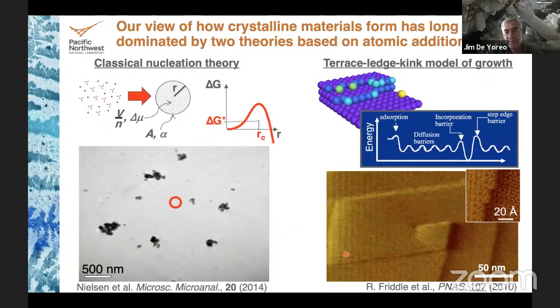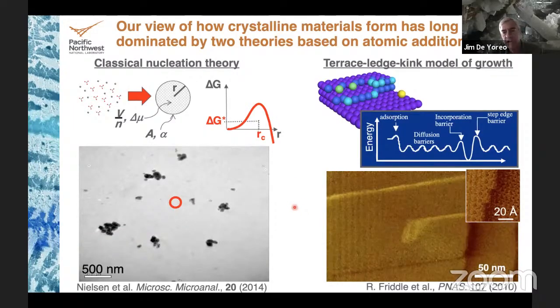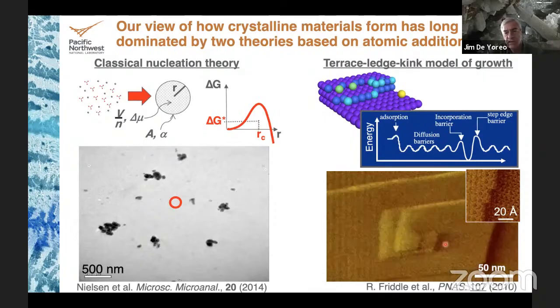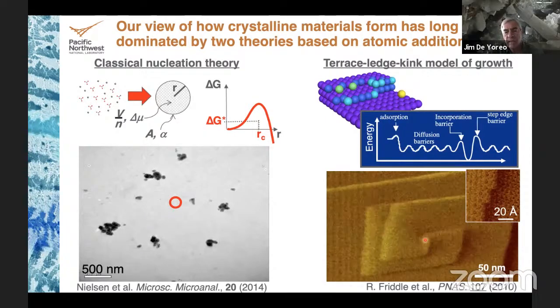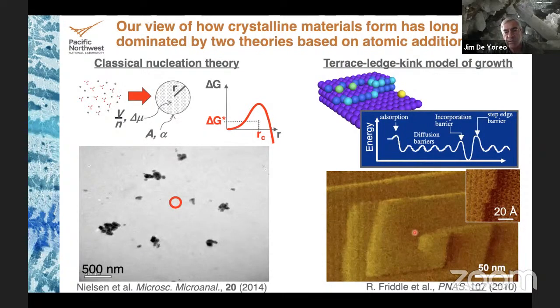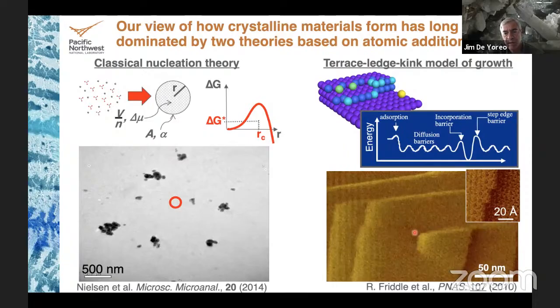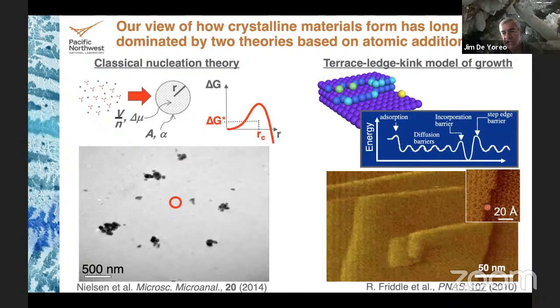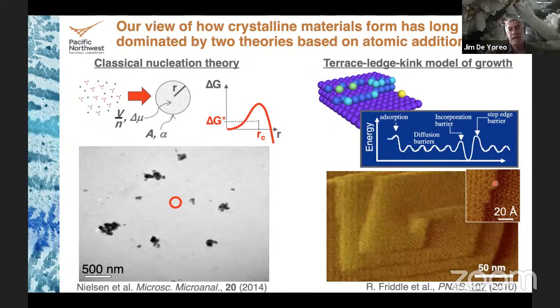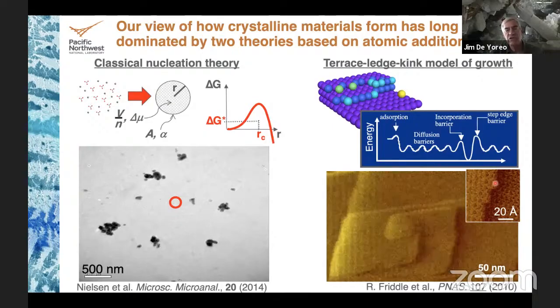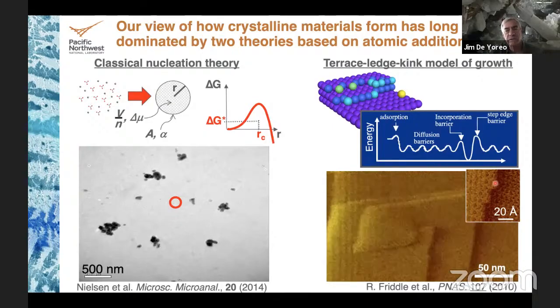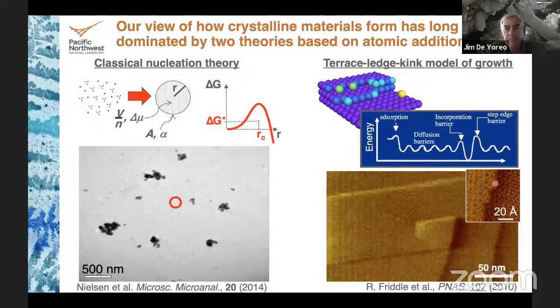And here's a nice example. This is a calcium oxalate monohydrate, just a crystal growing in solution. And here, because dislocations create a constant source of steps, it's where growth happens most rapidly. And at higher resolution, you can see the individual kink sites showing that this material is growing by the addition of individual molecules, not by some more complex species.